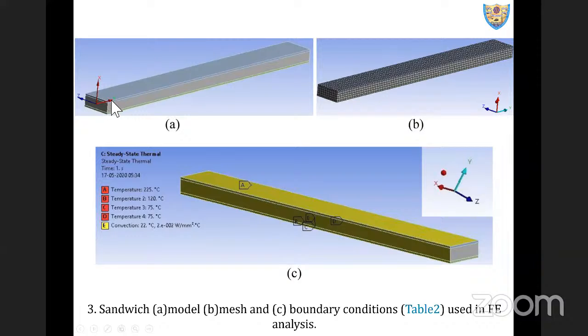So here in sandwiches, we have a bottom skin. Depending on the skin thickness and the total skin thickness you want, the number of layers will be decided. And then we have a core, and then again back to skin. So as I said, the sandwich structure consists of an upper skin, a lower skin, and a core, which is the middle portion. The printing parametric optimization is again carried out for the core first, being thicker. The filaments having the composition of H20 to H60 are fed to a fused filament fabrication based 3D printer. I have shown that 3D printer in one of the earlier slides.